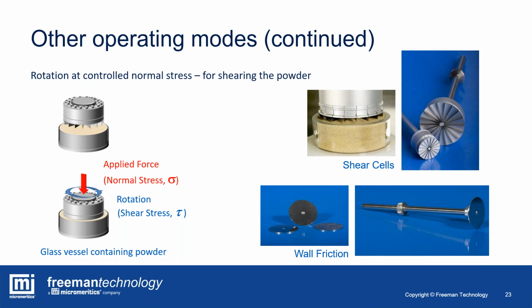If you change the hardware for a wall friction accessory, you can see in these bottom right images here, same methodology, except this time you're measuring the powder against that wall coupon, and you would obviously select something that would be representative of the process equipment so that you can understand what levels of friction or resistance to shearing exist between the material within the equipment and the equipment wall itself. And that can lead to justification or otherwise for example, changing the surface properties inside silos and hoppers.